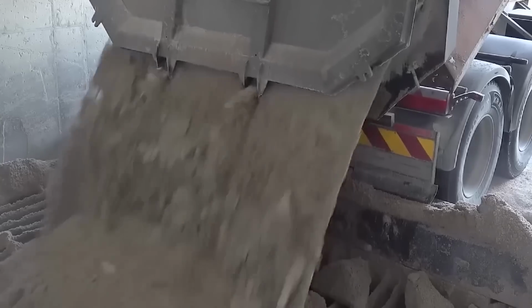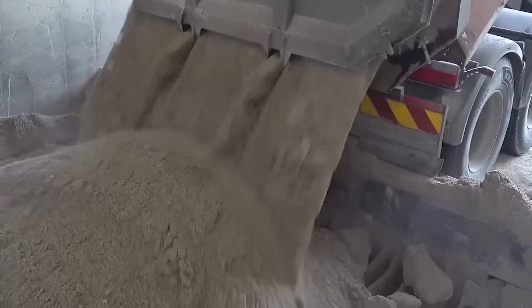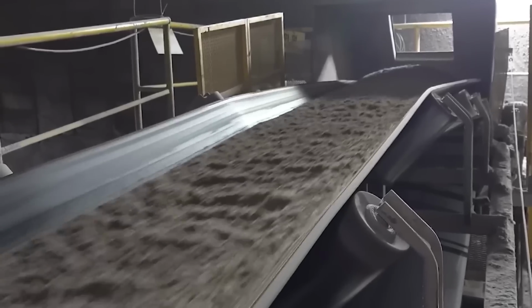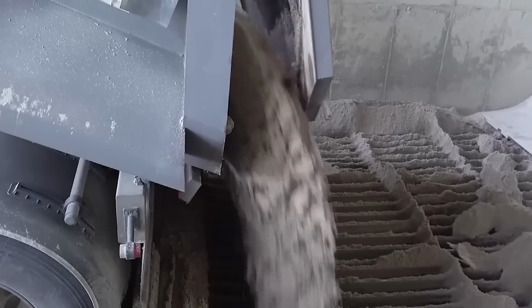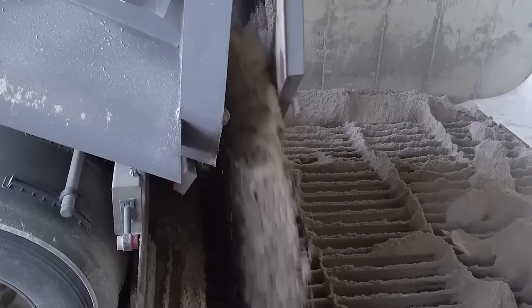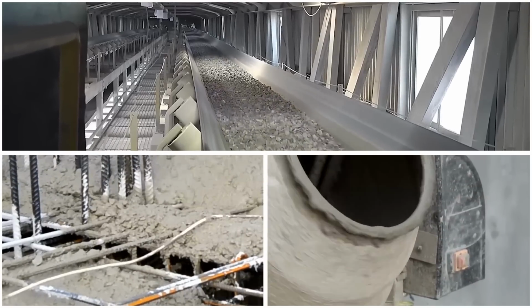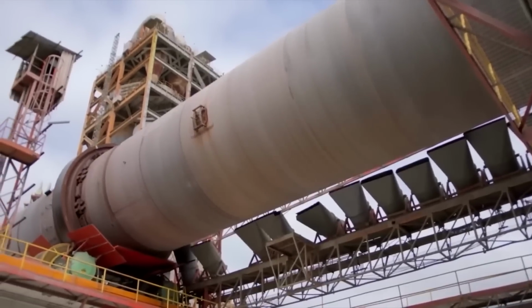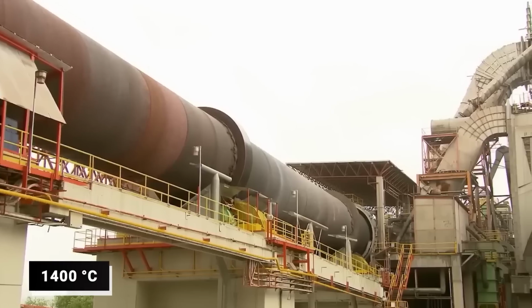As the raw materials fuse together to form clinker nodules, these need to be cooled rapidly and effectively. This is where the clinker cooler comes into play. The clinker cooler is a crucial component in the cement production process. After exiting the rotary kiln, the clinker is extremely hot, often reaching temperatures of around 1,200 degrees Celsius to 1,400